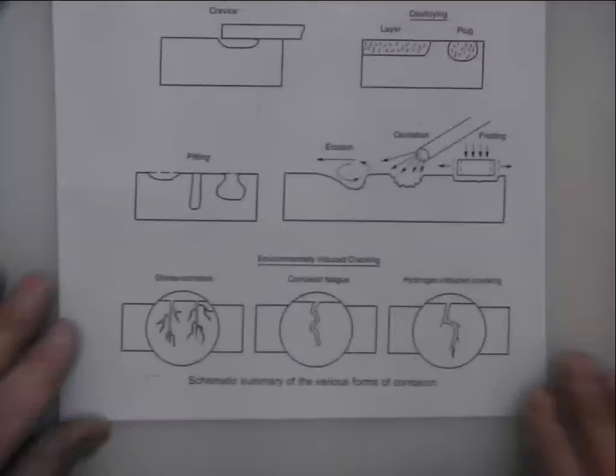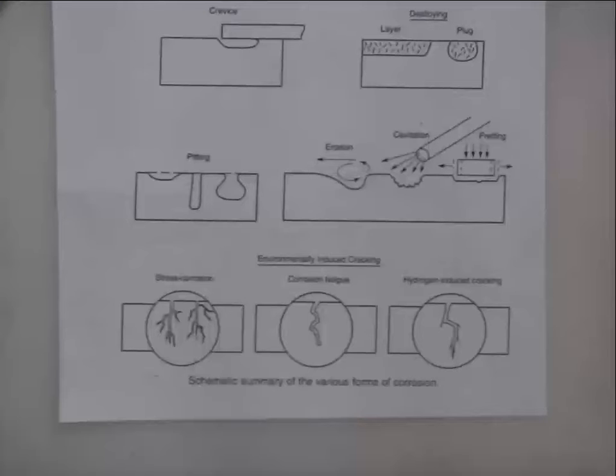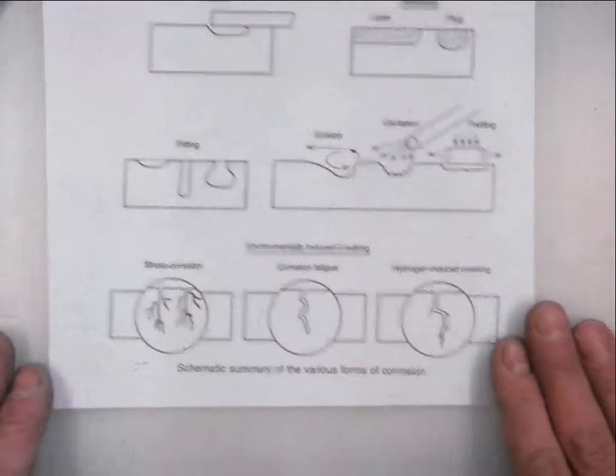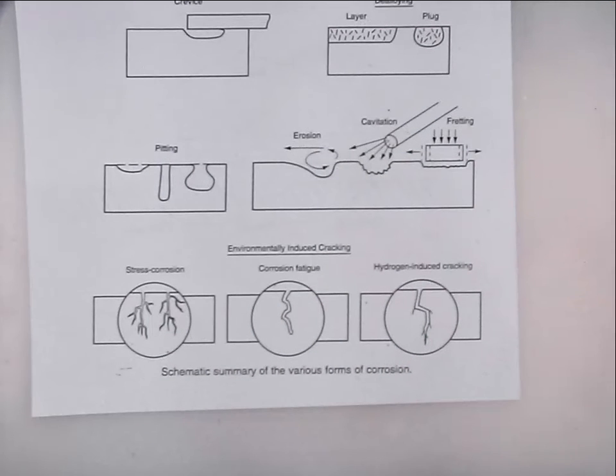You get anodes forming at low oxygen inside the capillary. So this is where the corrosion occurs, at the crack tips. And you get cathodes forming where there's loads of oxygen on the outside of the structure. Okay, so it's just like crevice. It's the same sort of thing. The difference from crevice is that there is some loading present. And what you're short of perhaps on this diagram is where the stress is, where the load is on the structure.